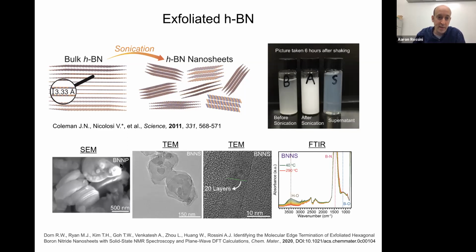So just looking at some SEM images, this is the boron nitride before we take it through the liquid exfoliation process. You can see sheets that are on the order of 500 nanometers in diameter, a couple hundred nanometers thick. After we do the exfoliation, we get much smaller nanosheets. We reduce diameters down to, say, between 50 and 200 nanometers. And if we look at the thickness of the sheets, they're around 20 layers of boron nitride thick.